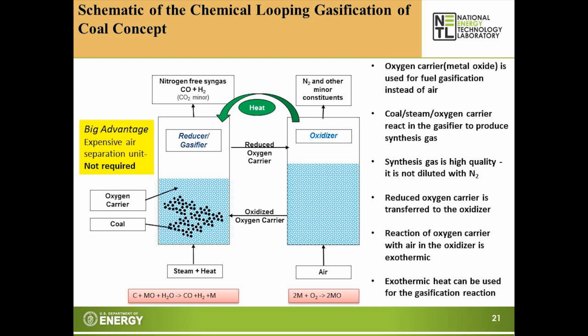The other process we have been looking at is chemical looping gasification, using oxygen carriers to produce syngas from coal. This process also has two reactors, the fuel reactor, or the reducer, or the gasifier. The coal is gasified using oxygen from the metal oxide oxygen carrier. And in the presence of steam, it produces syngas, carbon monoxide and hydrogen. And the syngas does not contain nitrogen because we are not using air.